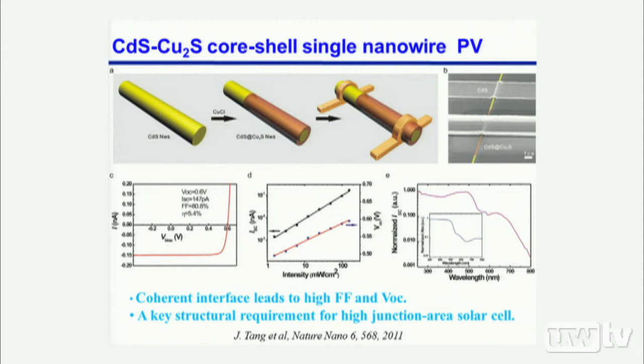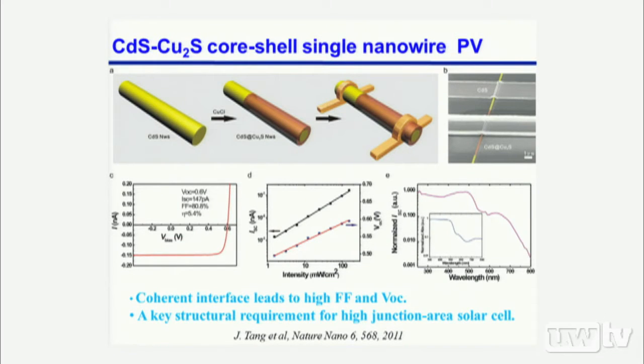Typically, as I mentioned, for many of these nanostructured solar cells we've looked at in the past, the fill factor would be in the region of 0.4 to 0.5. So this sort of fill factor is very much approaching the single crystalline version of the traditional solar cell. So indeed, by utilizing very mild chemistry, we demonstrate that we can create a high quality semiconductor junction that minimizes carrier recombination and maintains a high fill factor within these nanostructures.